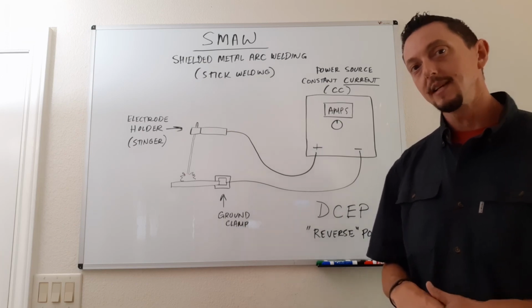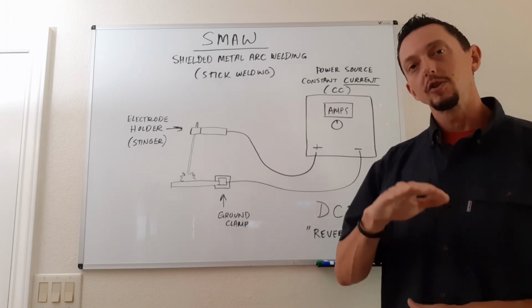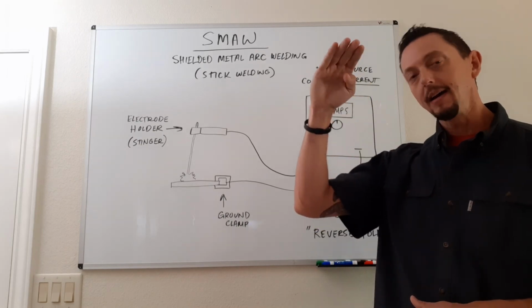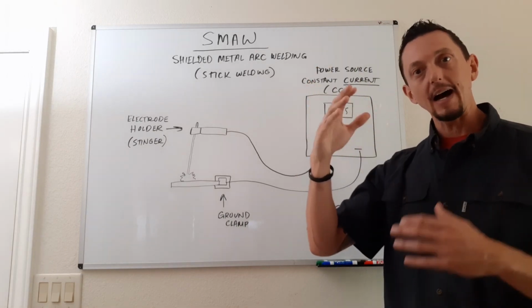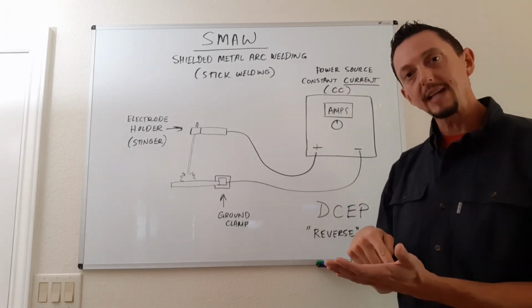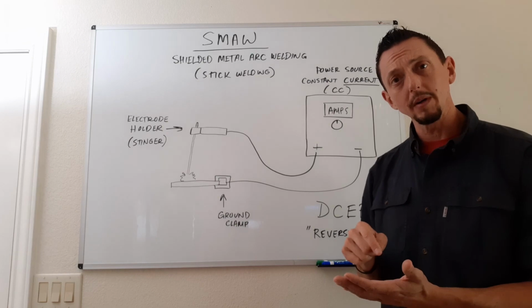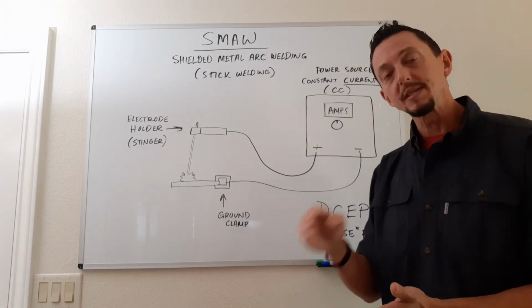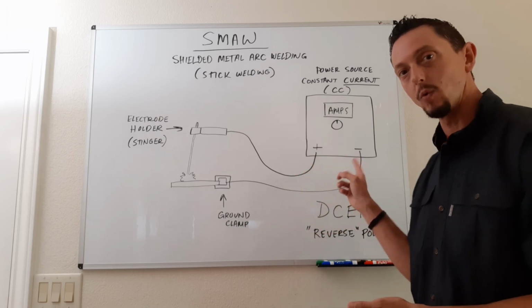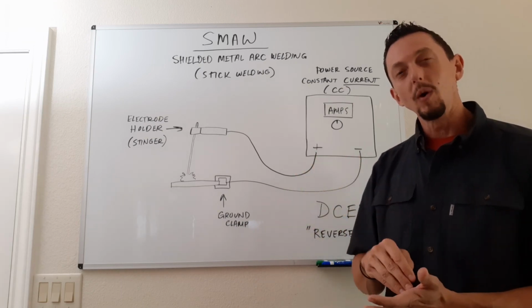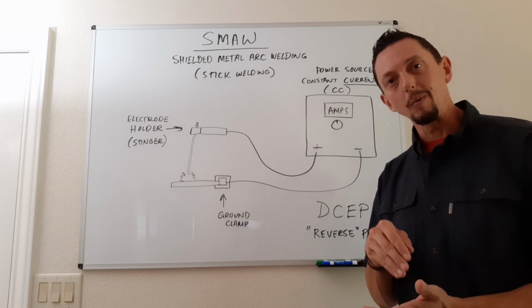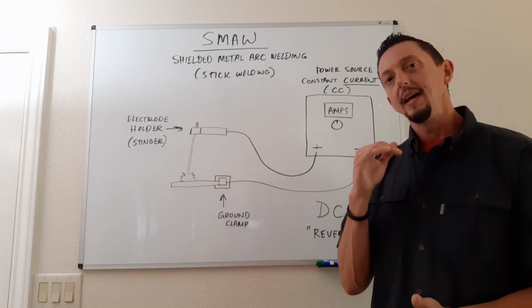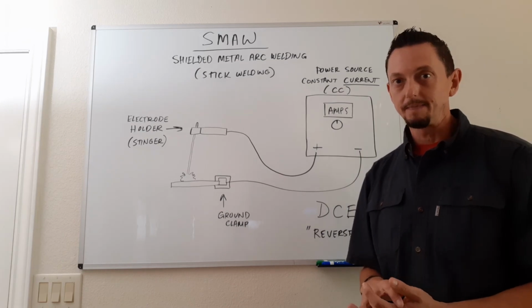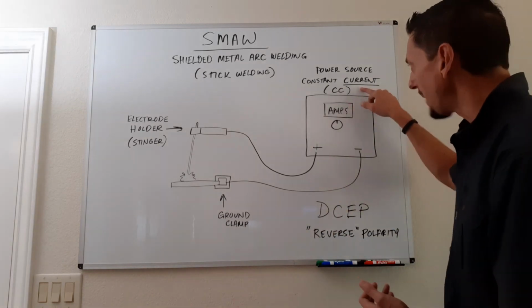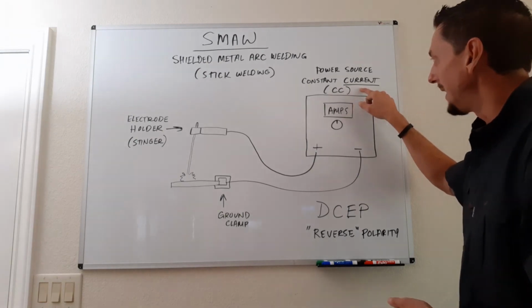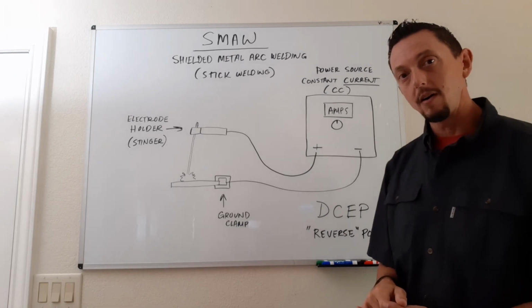So what this machine does is it tries to keep that current amperage consistent. It provides a high voltage to get the arc started, so it has a high open circuit voltage, and when you make contact with the base material, it will get the arc started, and then that voltage drops off, and it tries to keep a consistent amperage based on what you have it set at, no matter what the welder is doing in terms of how far away they're getting, how close they're getting to the work surface. That machine is going to try to keep that amperage consistent. So we're going to be using a constant current power source for SMAW, and amperage is our main parameter.